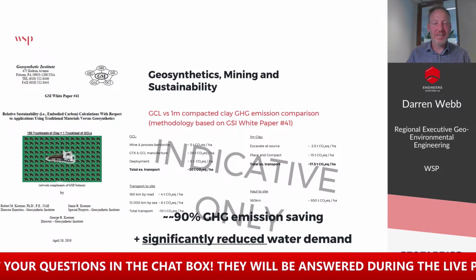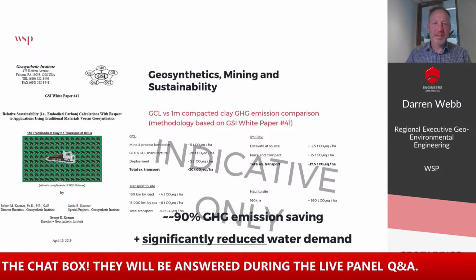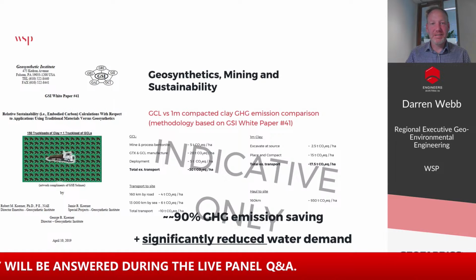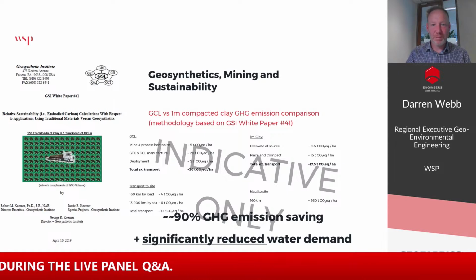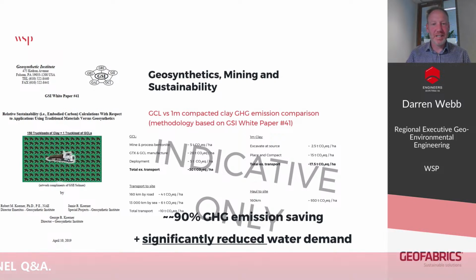If you're hauling clay a significant distance, then most of the time, or all the time, the GCL is going to have a lower carbon footprint than the clay, but obviously that's case by case. And the other important factor is that by using the GCL, we're able to significantly reduce the water demand, which in this part of the world was a significant impact or cost. If you're constructing with clay, the clay needs to be moisture conditioned and constructed to at least optimum moisture content to perform as a clay liner, whereas the GCL had reduced moisture requirements. So a really positive outcome in that regard.